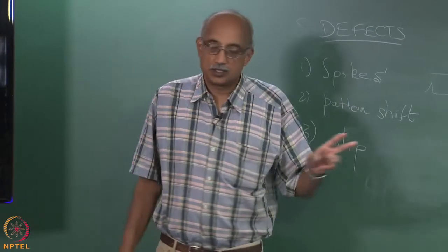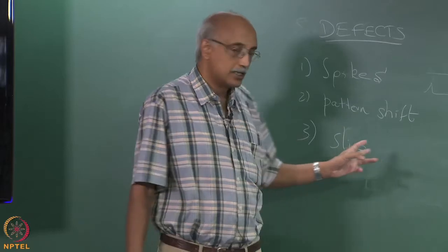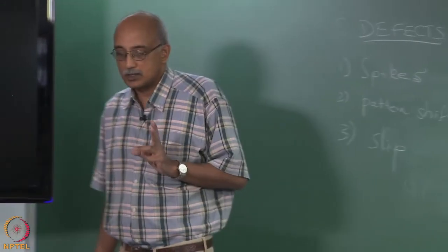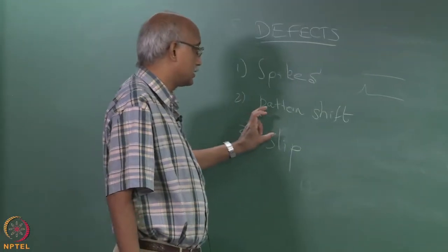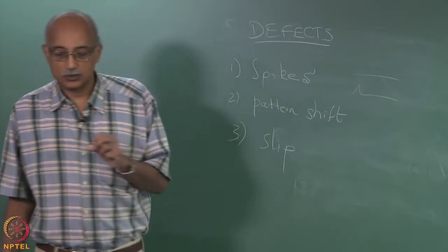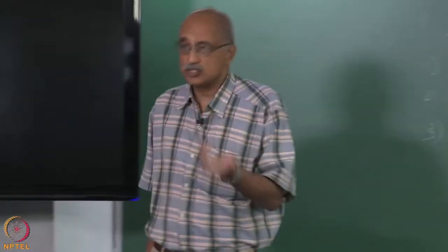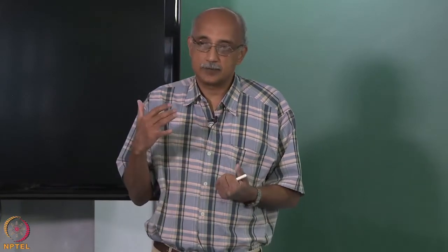Something like a pattern shift or a slip is more difficult to control, because that has to do more with the molecular behavior of the film itself. And the only way to address issues like this may be to either change your reaction conditions, change the species that you are using for the CVD process, or in some cases by introducing a post CVD step which can take care of these defects.